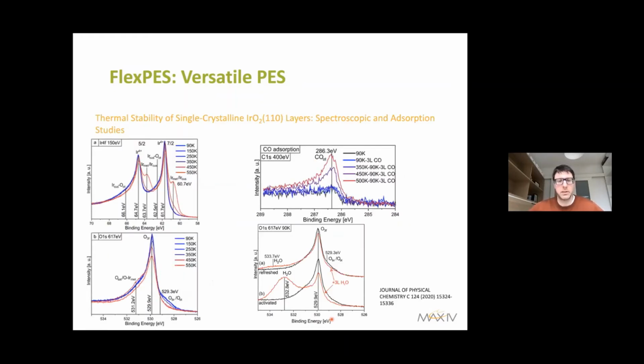One of the examples is a study of thermal stability and search for active phases for iridium oxide layers. What was found in this study is that, unlike electrochemical stability, the thermal stability of iridium oxide is quite poor. It already decomposes at temperatures above 450 K, and the formed reduced iridium clusters are active in binding, for example, CO or water, whereas the iridium oxide itself, freshly prepared, is totally inert.